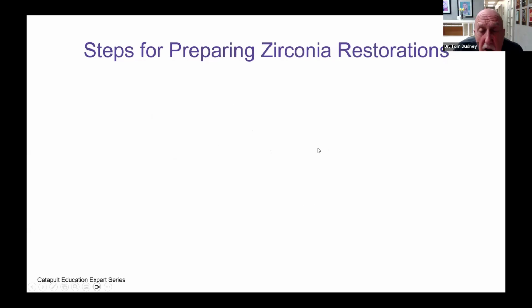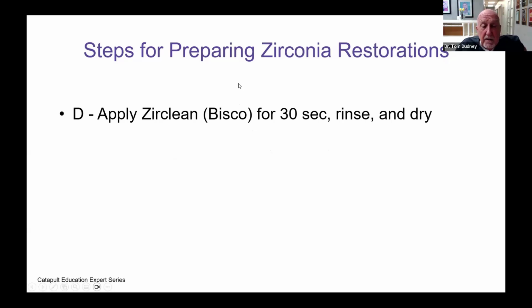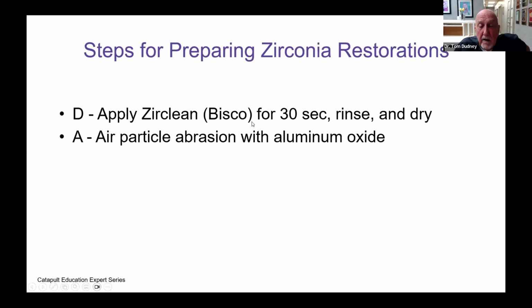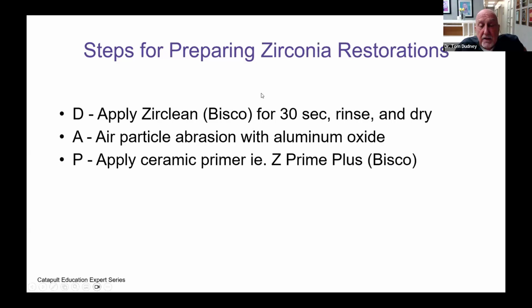If you are bonding zirconia, it's important to understand it's different from glass, okay? And you cannot clean zirconia with phosphoric acid because of its affinity for phosphate groups. You need to use a ceramic cleaner like Bisco Zirclean. 30 seconds, rinse and dry. That's all you have to do to clean zirconia. Then you want to air particle abrade it, and then you want to apply a ceramic primer, okay? This is like Z Prime Plus from Bisco. This is a ceramic primer that I use. This allows you to bond zirconia, and then you place your resin cement.